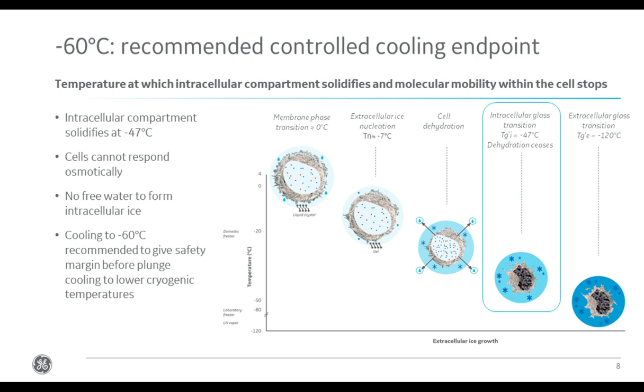When intracellular glass transition occurs, the cells are maximally dehydrated, so no further advantage of controlled rate cooling is seen, and it is safe to transfer to long-term storage without further control of the cooling rate. This exact point has been measured in a range of cell types. However, we would recommend cooling to about minus 60 degrees at least, just to give a bit of buffer room in case some transient warming occurs during transfer.